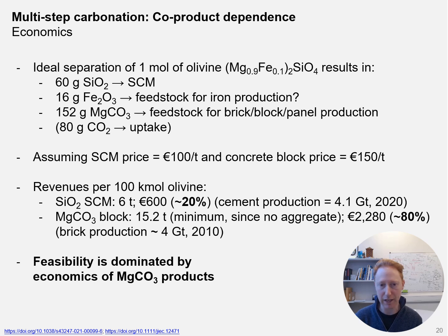If we do a back of the envelope calculation here, we can work out that about 20% of the revenue will be going to the silica-rich supplementary cementitious material, and about 80% of the revenue will be going to the magnesium carbonate block. So the economics of this process is dominated by the selling of the magnesium carbonate product, and this means that the viability of producing silica-rich supplementary cementitious materials from this process depends on the viability of selling magnesium carbonate products.